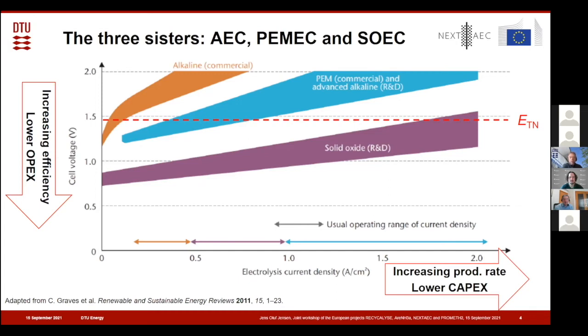So we have this. These are the families, and then we will see that the PEM electrolyzer is more efficient than the alkaline electrolyzer, and that is often claimed. But in reality, they are just operated at an acceptable efficiency, and that would be somewhere within this shape that I've added now, called normal operation. So if you compare the actual conversion efficiency of PEM and alkaline systems, they are very much the same. It is just that the PEM system has such a much higher rate capability, so you can do with a much, much smaller system. And that makes it very attractive, of course.